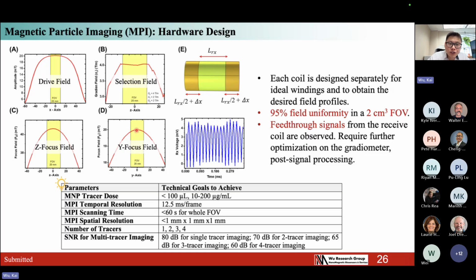These are the slowly changing fields to switch the location of the field-free point in the space. So you can see almost 95% field uniformity in the 2 centimeter field of view. This tells us that this coil design, with the dimensions we entered here, is able to generate a uniform field for 3D scanning in the field of view we want to scan.